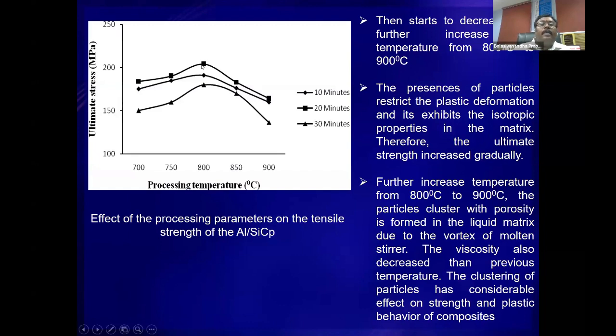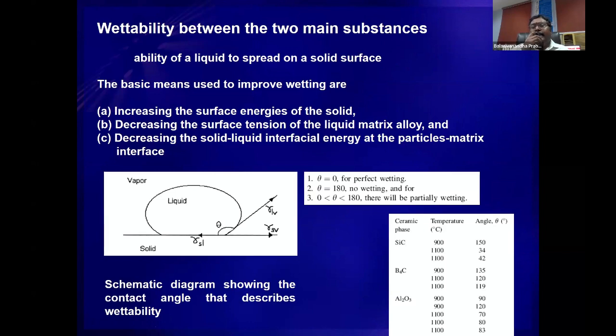See, when you have 800, you have a homogeneous distribution. As a result, you get good mechanical strength compared to the 700 degree processed condition. But in the 700 as well as 900 degree conditions, the strength is declining. That means one has to optimize the temperature to get a homogeneous distribution. So the temperature effect we have studied.